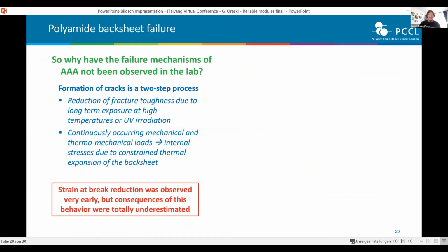So the interesting thing is these cracks have not been observed in the lab. Why? Because this crack formation is a two-step process. First, we need heat and UV to reduce the fracture toughness of this material. And then we need a continuously occurring mechanical and thermomechanical load that causes these internal stresses and is actually the crack initiating force. This strain at break reduction was observed back then. I remember talks with the guys, but the consequences were totally underestimated by everyone in the market, or at least everyone I talked to. So what was done?